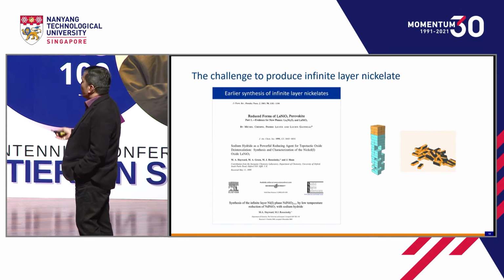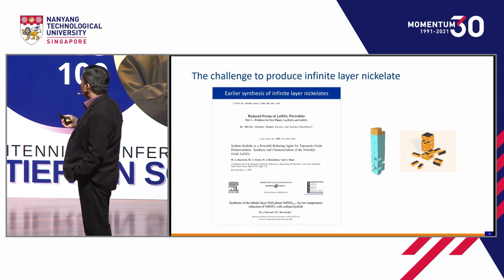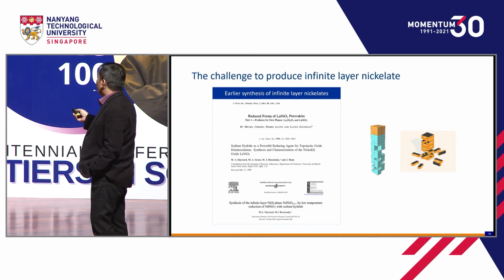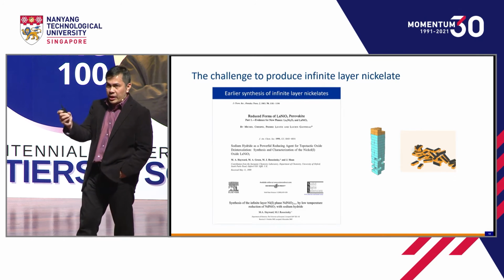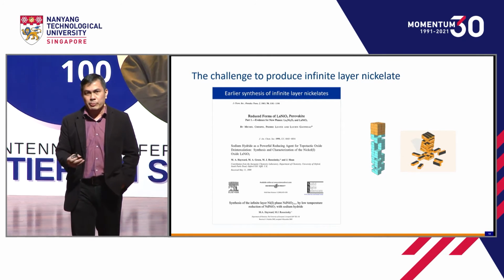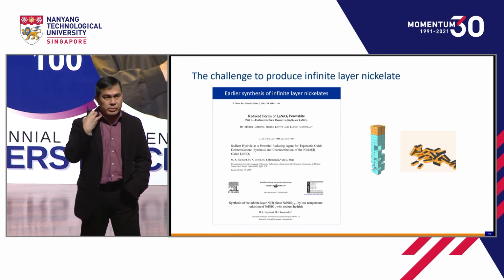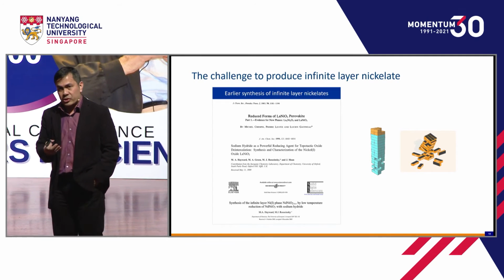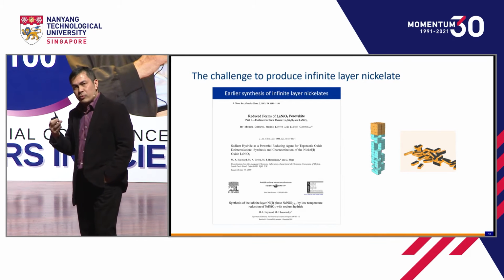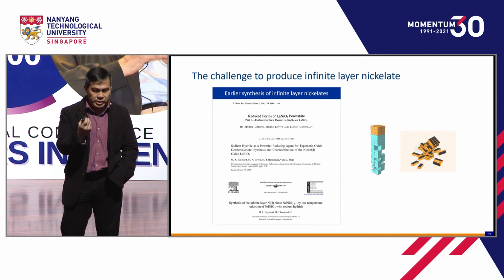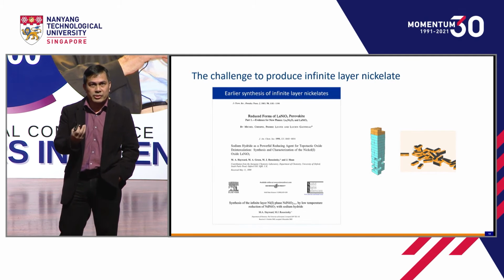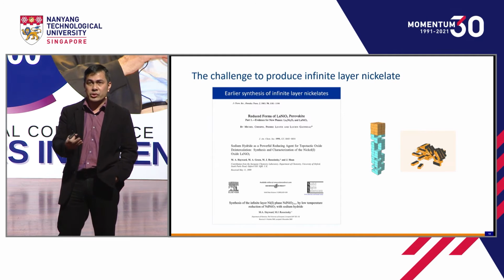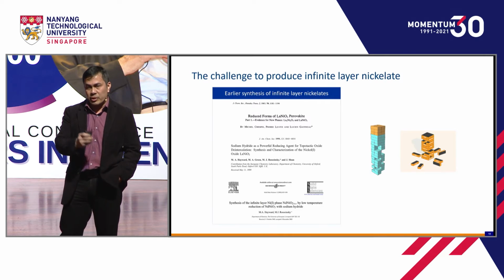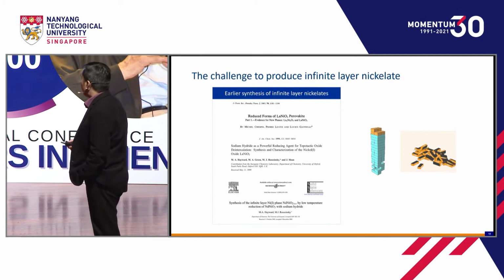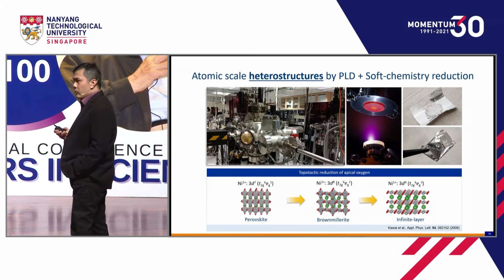So people have been trying a lot, and just to summarize, this is what you can visualize in this way: you start to build the structures, but then at the same time you need to remove atom by atom. If this is not done properly, the structure will just collapse, and then you don't produce these infinite layer structures. And that's what has happened. Mostly people have been working using powder or crystals, and this somehow cannot stabilize the infinite layer structures, even though you can try to do this atom removal in a controlled manner. So the key point, it looks like, is to try to produce this in a more controlled way.